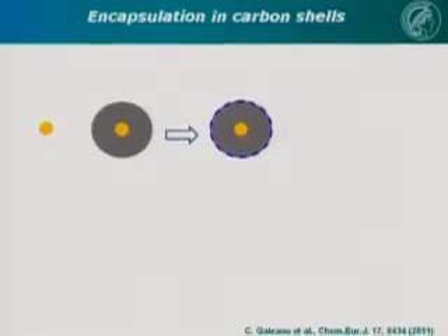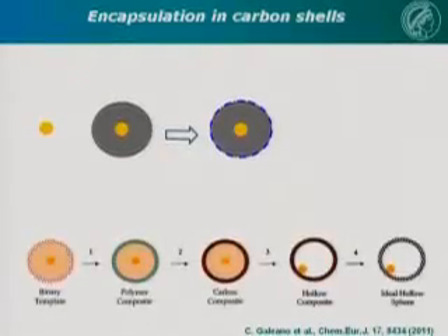But what you can do to create a carbon shell is, you stop at this point here, you don't leach at this point, but you take this first product as a binary template and infiltrate the pores in the zirconia with some sort of polymer. This can be furfuryl alcohol, but this can be many other polymers which carbonize well. Then you carbonize, heat at high temperatures, 800 centigrade in protective atmosphere or vacuum. So then you create the carbon-zirconia composite coated on a silica, coated on a gold particle. And then you can leach either separately, first the silica, then the zirconia, or both at the same time. And at the end, you get gold in a carbon shell.